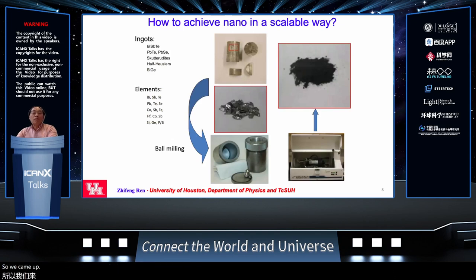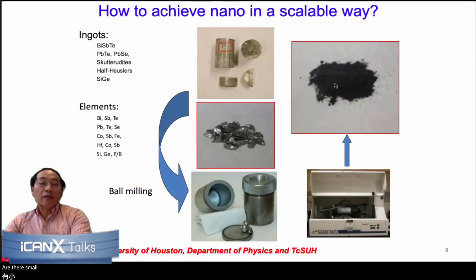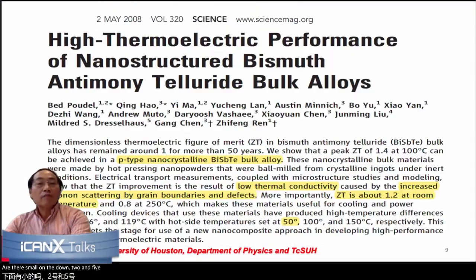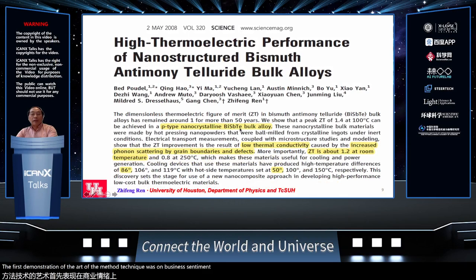So we came up with this ball milling process, which is an industrial process. It can handle hundreds of tons of materials per year. And it's very easy: you put either the alloys or the elements into ball mill jars. These jars could be very small in the lab, 25 milliliters, and in industry could be many gallons or many cubic meters in size for milling. Then through mechanical shaking, after some time, you get very small powders, down to 10, 5, or a few nanometers.